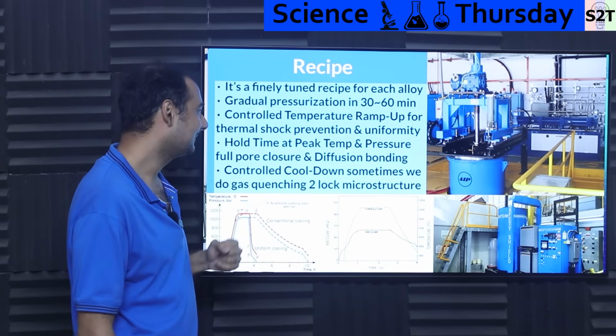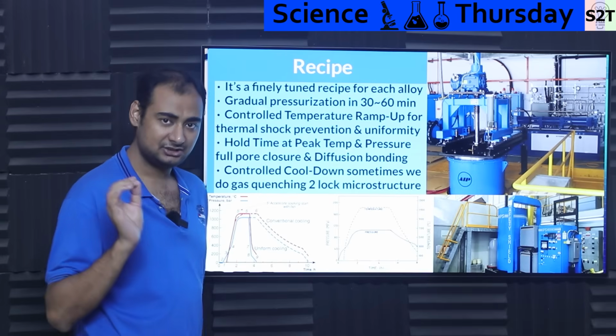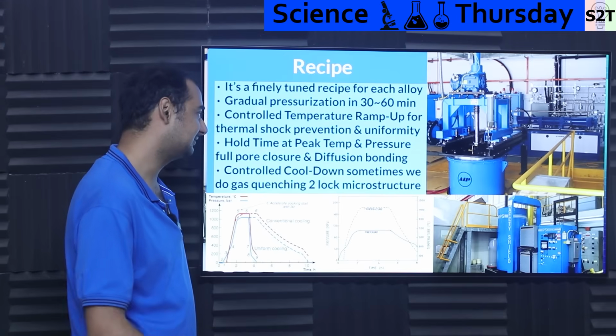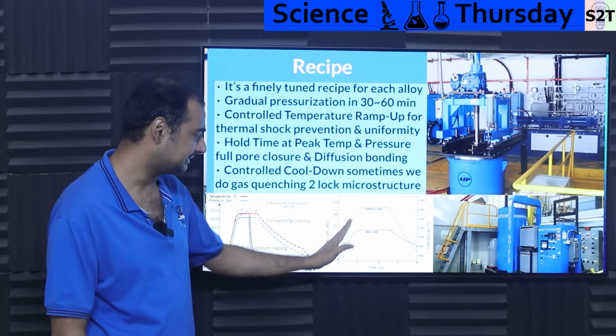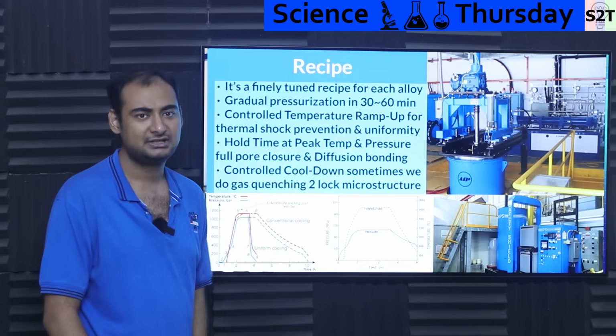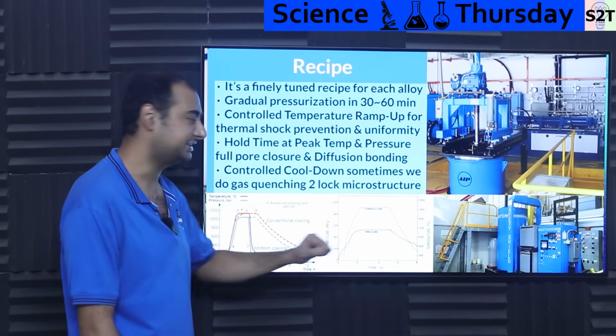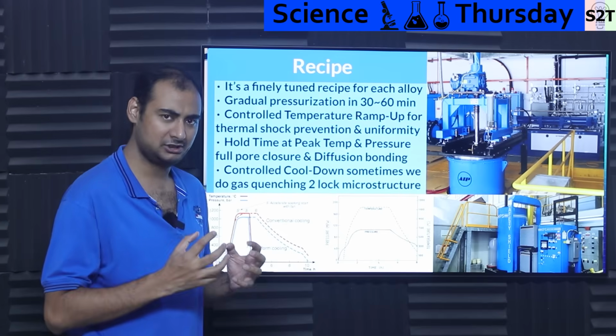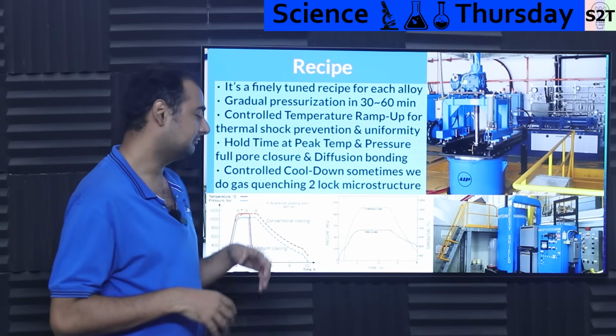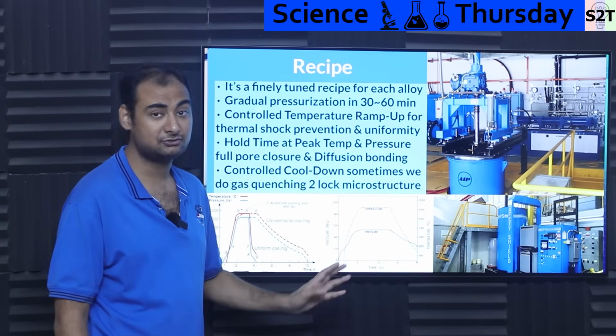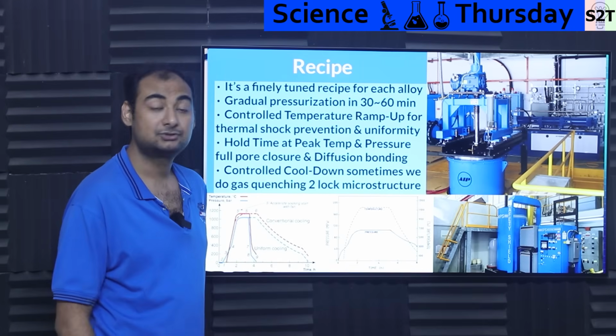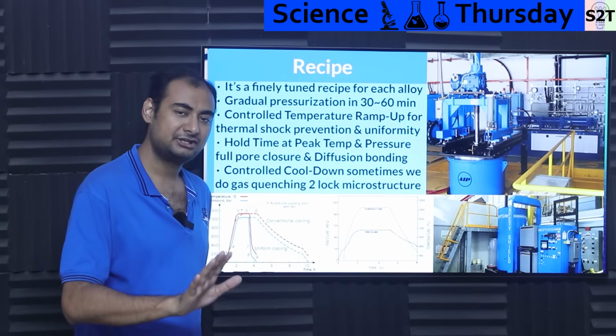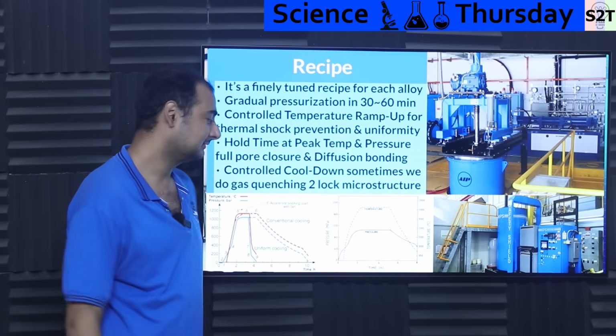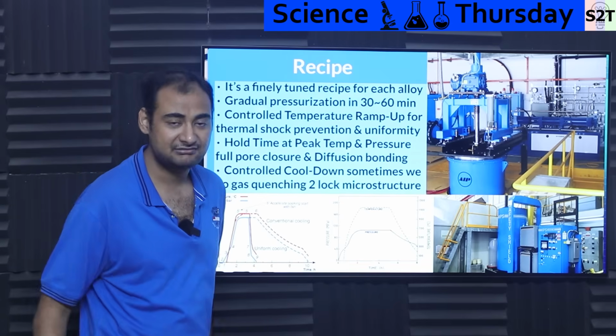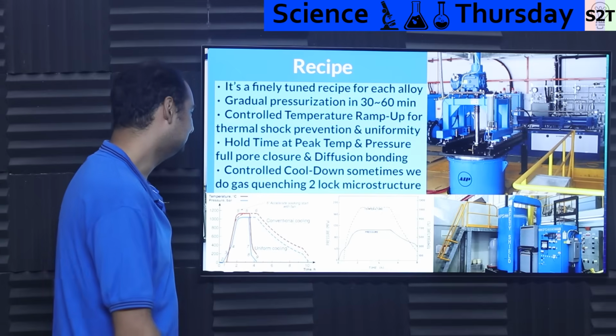So you slowly ramp it up, and again, slow temperature ramp up is critical, otherwise it will not work. And pressure is also ramped up, depending on your alloy, something like this graph would be created. And then you hold it. Once you reach the target temperature and once you reach the pressure, you hold it. Now, depending on the product requirement, holding could mean turn it on, come back tomorrow. I'm not even joking, some of them take 8 hours to 15 hours. So you hold the time.